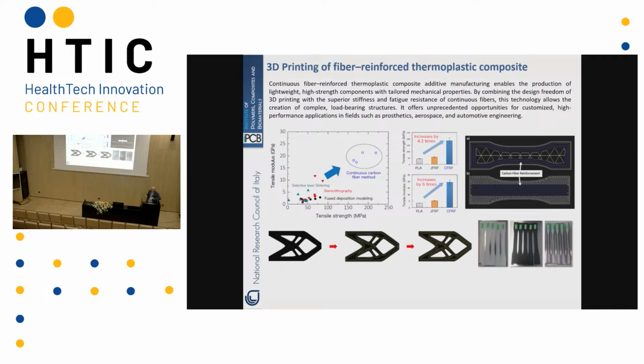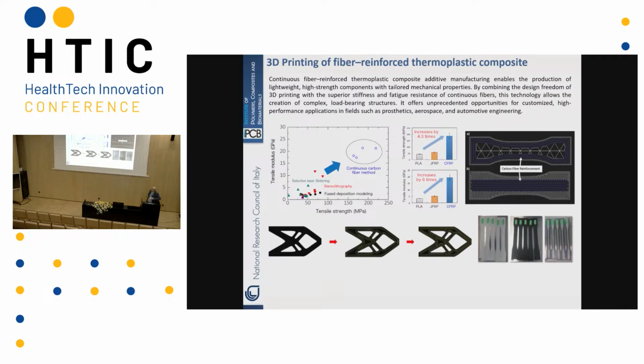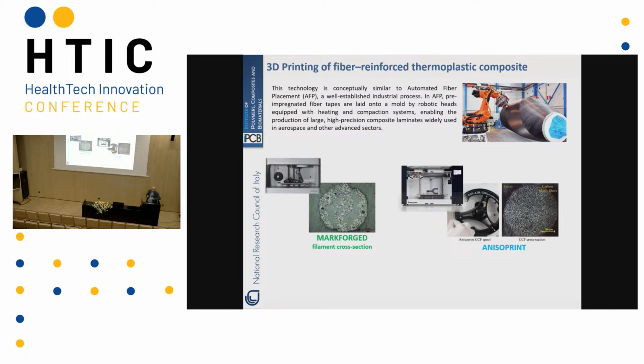It's quite a new technology. It's formally similar to what was generally used in some industries, automatic fiber placement, but in that case we use thermoplastic material, not thermosets, and we don't use molds, and we cannot apply pressure. So for that reason, we have a strong problem related to the presence of voids inside the structure that we are printing.